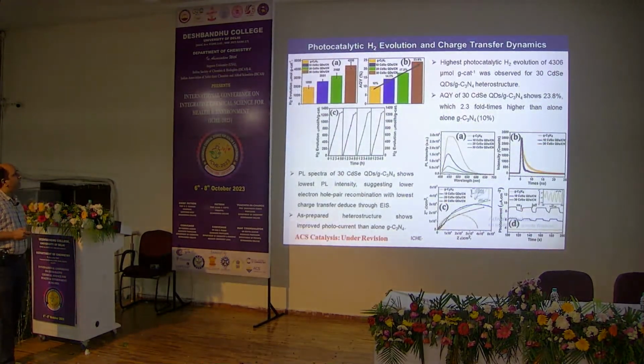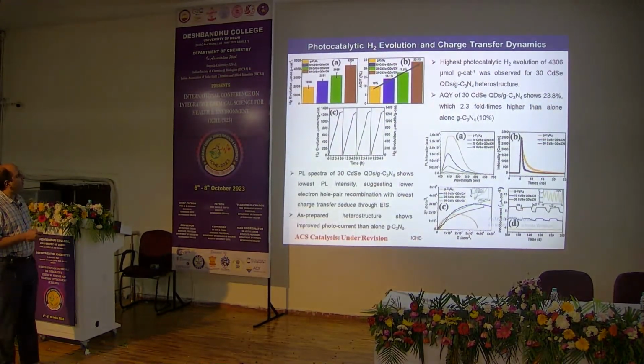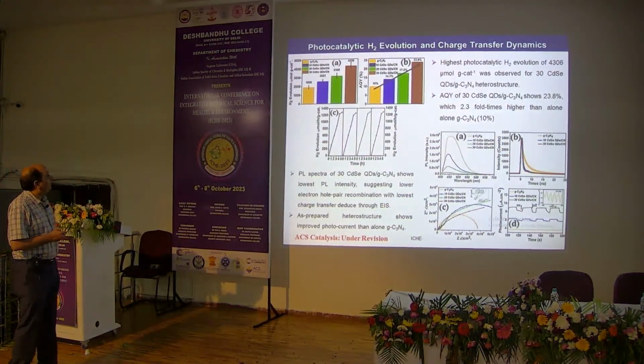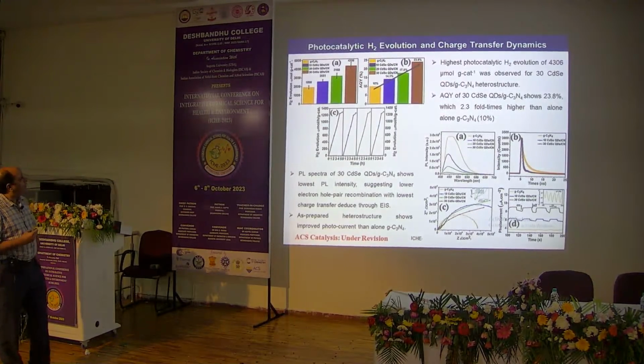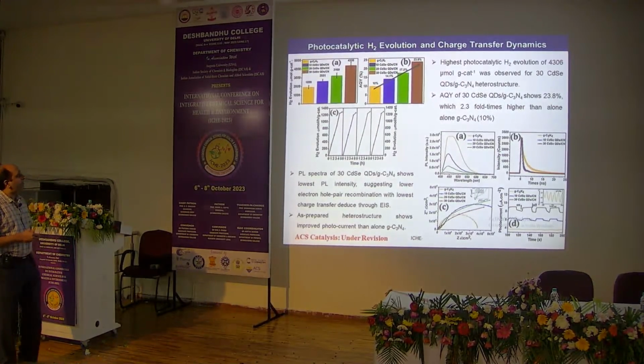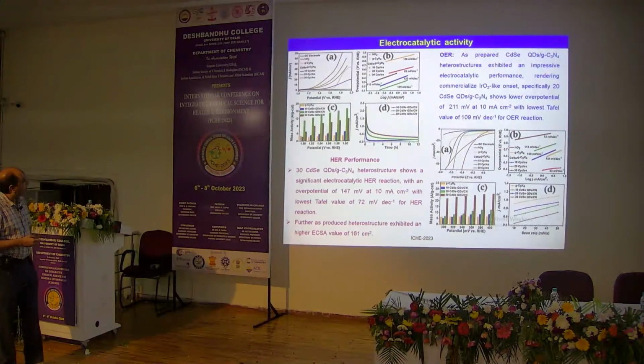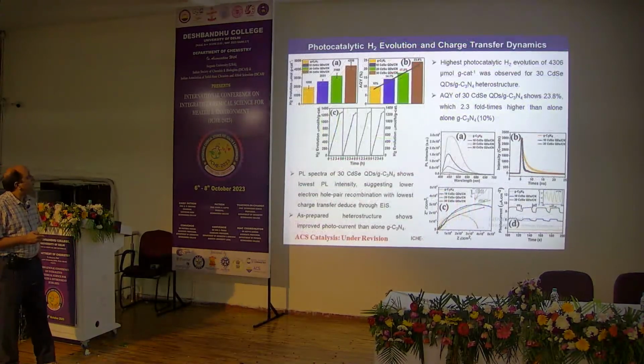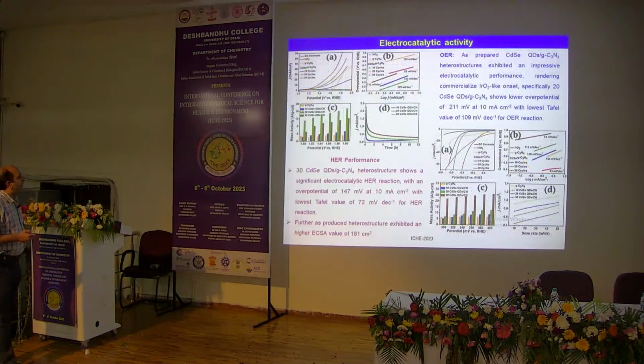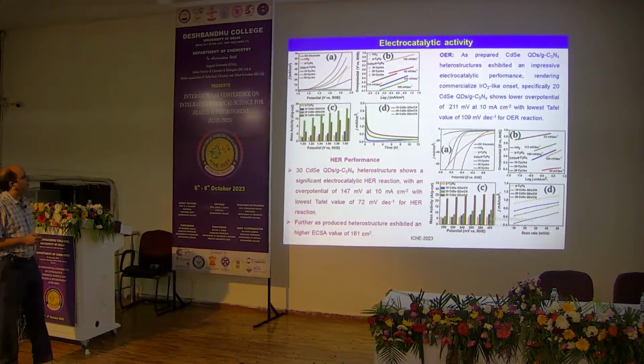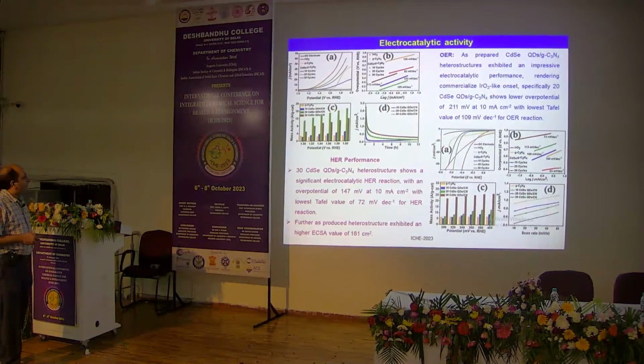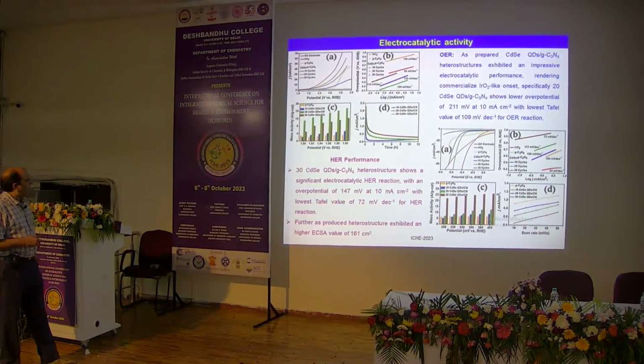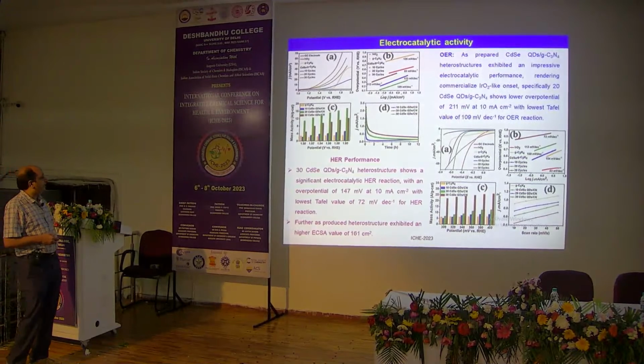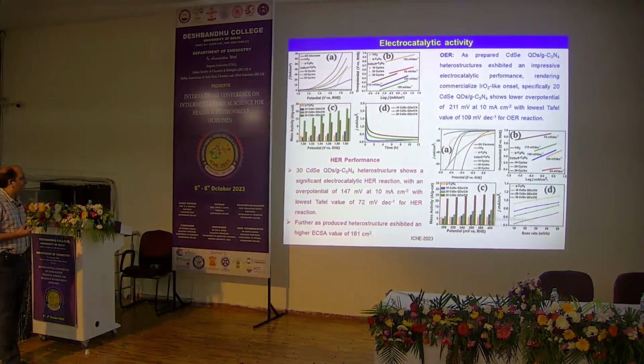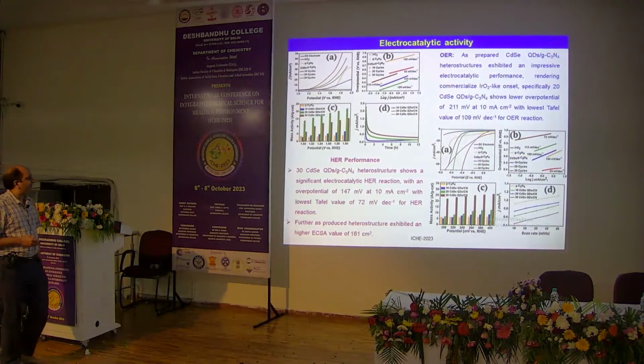And here the hydrogen evolution could be seen, a very high amount of hydrogen could be obtained, which is around 4.4 millimole per hour per gram with an apparent quantum yield of 23.8%. And these are the electrochemical investigations, and here the 30% CdSe quantum dots over graphitic carbon nitride heterostructures could give the significant HER reaction.